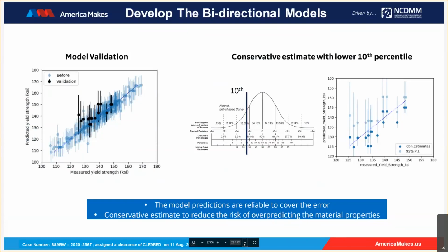On the right-hand figure, the conservative predictions are demonstrated in the solid blue dots. You can see the mean value has been significantly lowered using this conservative estimate. Now all the predictions are close to the measurements, and for most cases, more than 70% of cases, it's lower than the measurements. That lowers our risk of being optimistic and overpromising the design properties. So next slide, Neil, please.